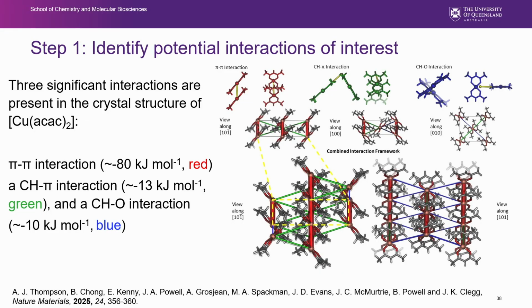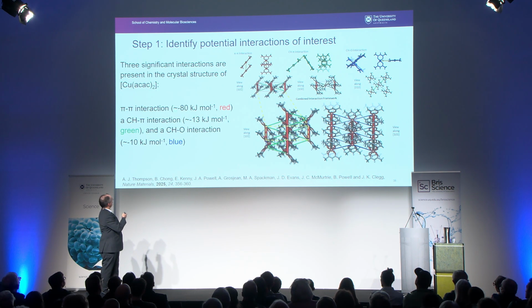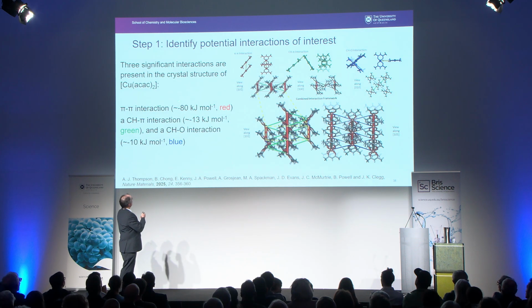So the first thing we need to do is to identify the potential interactions of interest. Now we can use computers to help us do this, but just by looking at the crystal structure, we've got a good idea. Right? We said that there was a strong pi-pi interaction in one direction and weak interactions in the opposite direction. But we can use the computer then to put some numbers on this. So we can verify that the pi-pi interaction, shown here in red, is much stronger than the weaker intermolecular interactions, the green one and the blue ones that are perpendicular to that. The numbers here don't matter, other than 80 is much bigger than 13 or than 10.